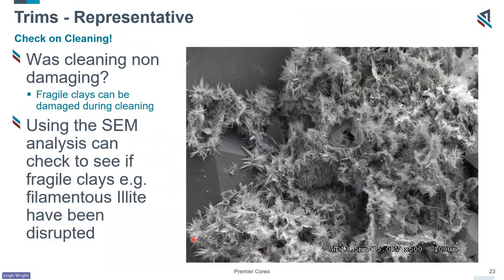And as Ben mentioned briefly before, we're checking the samples with the SEM to make sure that the clays are correct. And as a geologist with a background in formation damage, seeing a lovely set of clays here, because these are extremely fragile, we know that this sample's not damaged. So again, it's making sure that the prep, the understanding of the core material, the process and checks throughout the process is correct.